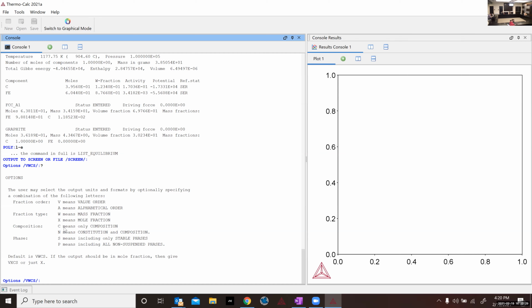The third one is either C or N. C stands for composition. N stands for composition and constitution. Constitution means how much are on each one of the sublattice sites. So if we're talking about BCC and there are 2 atoms per unit cell, and we're looking at a BCC phase that has been described in terms of 2 different sublattices for BCC or B2, it will tell us how much of each element is on each one of those sublattices.